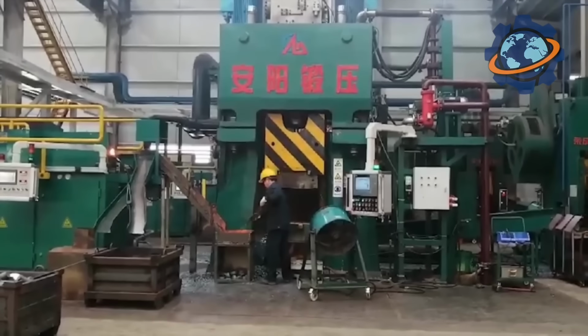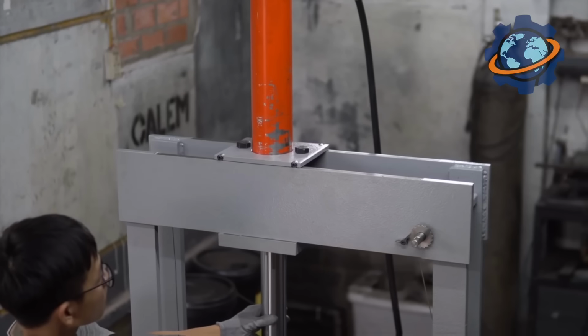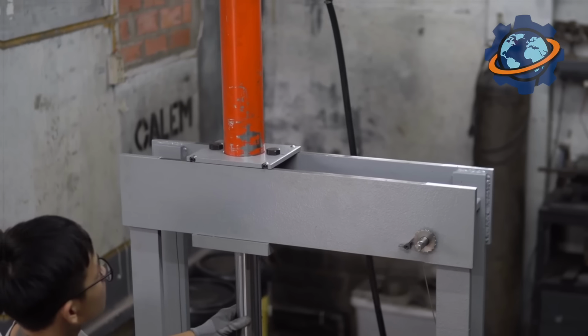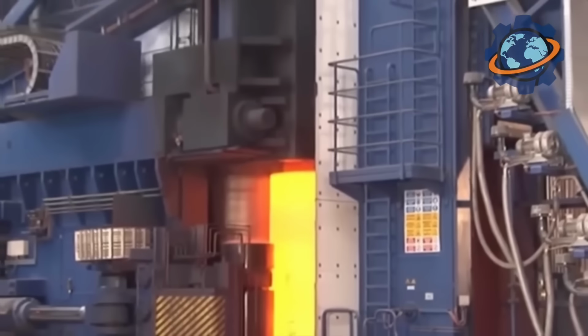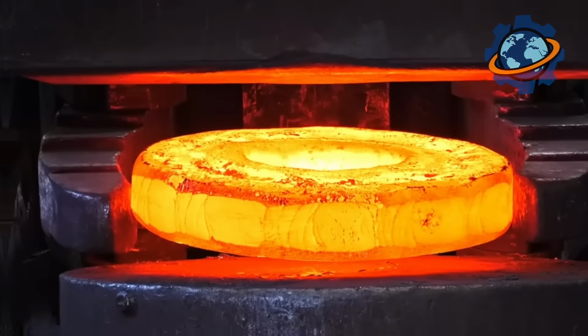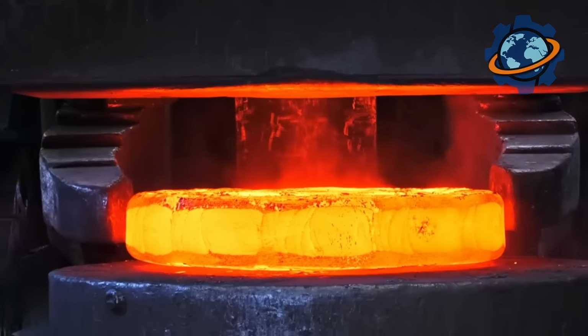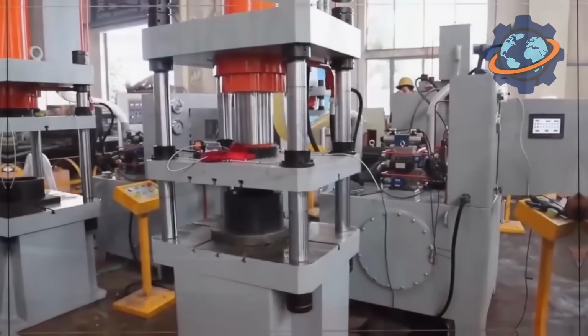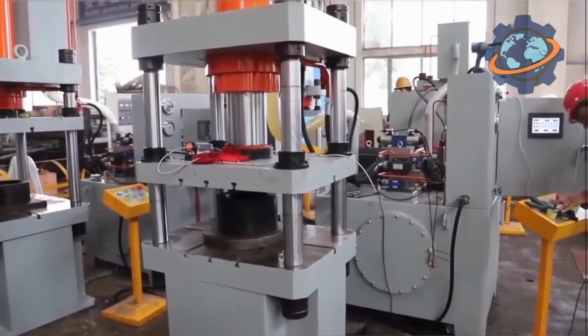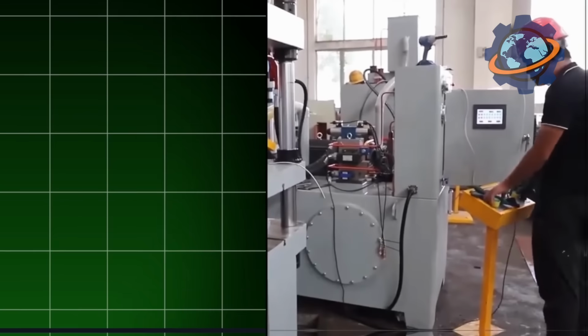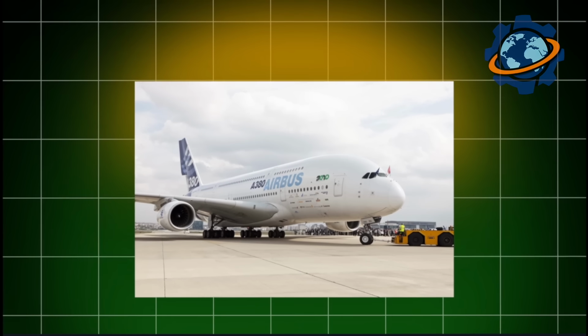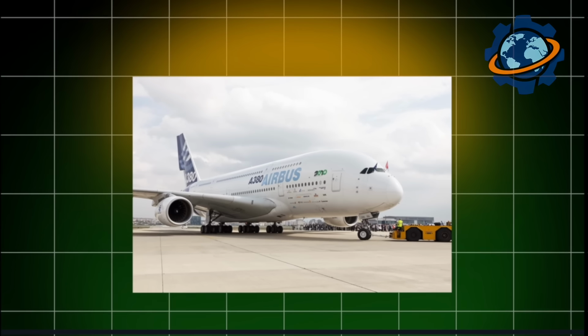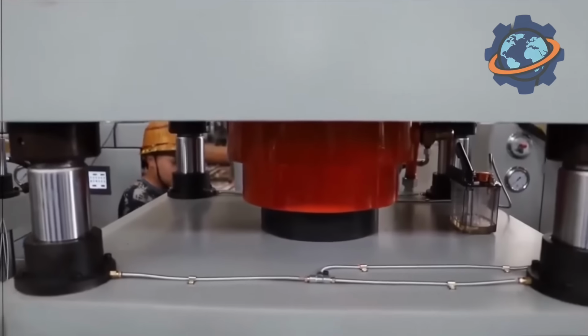So here's the secret promised. These monster presses exist because physics favors size. Larger presses forge larger components in single operations, eliminating joints where failures initiate. Every weld introduces heat-affected zones with altered crystal structures becoming crack paths. Every bolted joint adds weight and complexity. Seamless forgings eliminate these vulnerabilities entirely. That's why the Airbus A380's wing ribs come from single forgings. No welds, no joints, just continuous metal flowing across 20-foot spans.